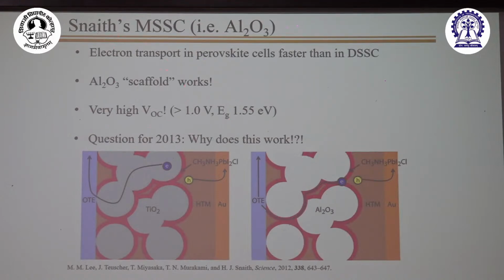Okay, one of the interesting things was Snaith's alumina. Instead of TiO2, he used alumina, and he did both, right? So just to show that it works with both these things. Although nobody is using alumina now, at that time it showed that all these electrons were traveling like this and the holes were traveling in the opposite direction, so it did not need TiO2. And they got a very high voltage to begin with. The band gap was 1.55, and you can get up to 1. Today we can get up to 1.2 volts, okay? Why does this work at that time?